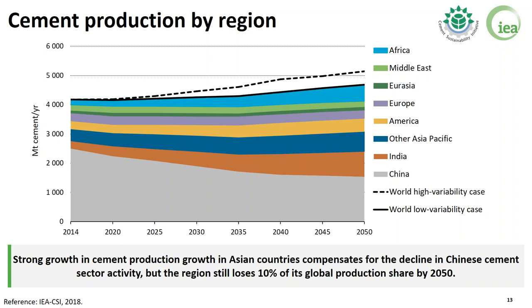So in terms of regional breakdowns, you can see here that towards the long term, we are expecting slower activity in the cement sector in China, which is shown in gray at the bottom of the chart, which in any case is compensated by strong growth seen in other Asian countries, namely India. This makes the whole Asia region stay relatively similar in terms of overall cement production over time, but still lose 10% of its contribution to the global production level. Of course, you also see other regions experiencing growth, especially Africa and Latin America.